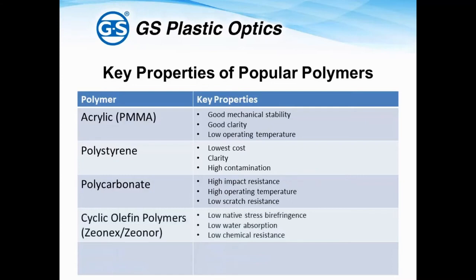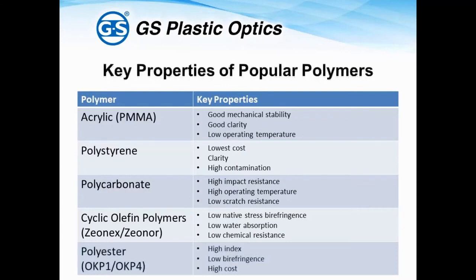Cyclic olefin polymer, COP, is a family of plastic resins with low native stress birefringence properties and relatively high heat distortion temperature. Zeonex, a resin developed by Nippon Zeon, has a remarkably low water absorption value of less than 0.01%, compared with polycarbonate 0.2% and PMMA 0.3%. GS Plastic Optics has developed considerable expertise in injection molding optics with this resin. OKP is a special polyester for optical use with high refractive index, extremely low birefringence, and high fluidity. It is significantly more expensive than other thermoplastics used for optical molding.